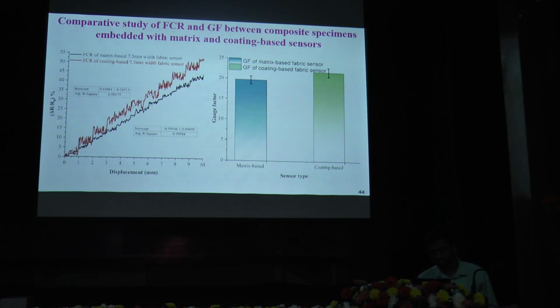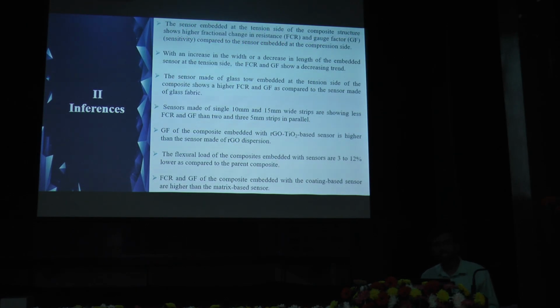Here you can see that in case of the coating based sensor, the gauge factor is comparatively higher than the matrix based method. Inferences from this study: sensors made of single 10mm and 15mm wide strips show less FCR and gauge factor than 2 and 3 parallel 5mm strips, and the gauge factor of composite embedded with RGO-TiO2 based sensor is higher than sensors made of RGO dispersion.